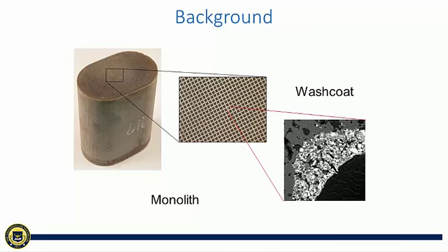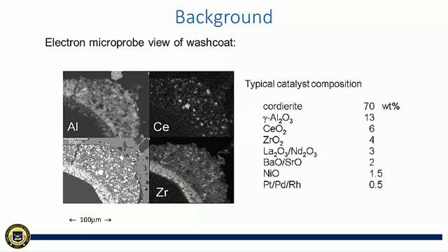But there is another level of structure, easily seen with a magnifying glass, consisting of the so-called washcoat, which contains all of the important ingredients of the catalyst. These electron microprobe images of a small cross-section of the washcoat layer provide some idea of the real complexity embodied within the catalytic converter. A typical formulation contains more than half a dozen different oxides, each of which has been carefully chosen to perform a specific function.